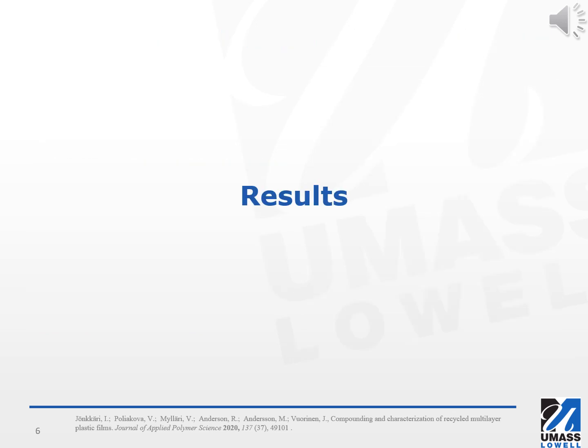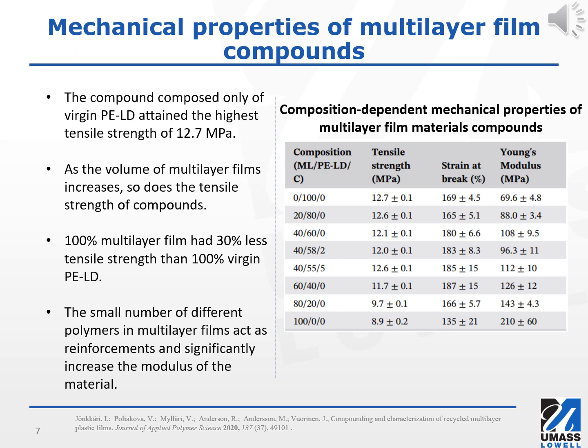So now I will proceed to discuss the results that were acquired from the experiment in a logical fashion. As a part of the result explanation, this slide demonstrates the mechanical characteristics of multilayer film compounds. It is pretty much evident from the table that the compound consisting exclusively of virgin LDPE achieved the highest tensile strength of 12.7 megapascal.